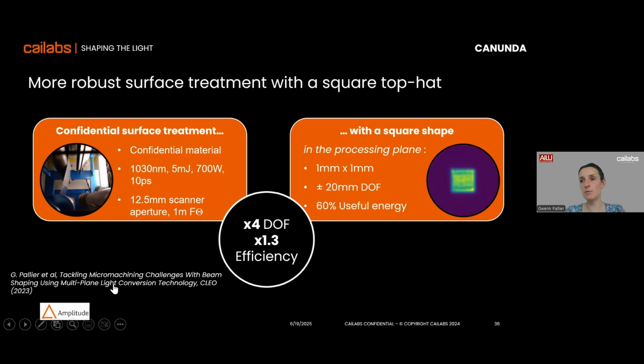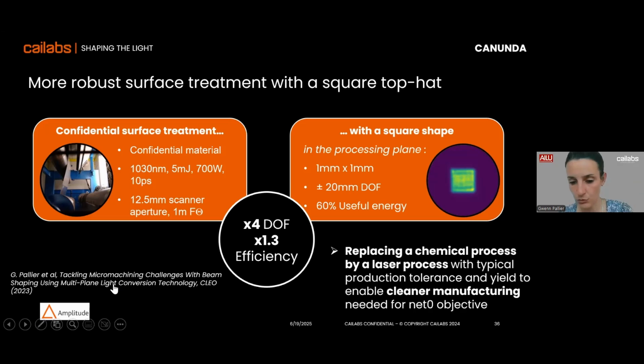And at the same time, since they want to really go fast, they want all the energy which is in the laser pulse to be useful. So we were really calculating how much of the energy is really efficient to the process. And we managed to actually have a depth of field 4 times larger and at the same time a better efficiency compared to other technologies. The whole idea is that only by doing something at the same time very tolerant and very efficient, you can really implement this laser process in the industry to replace non-laser processes.